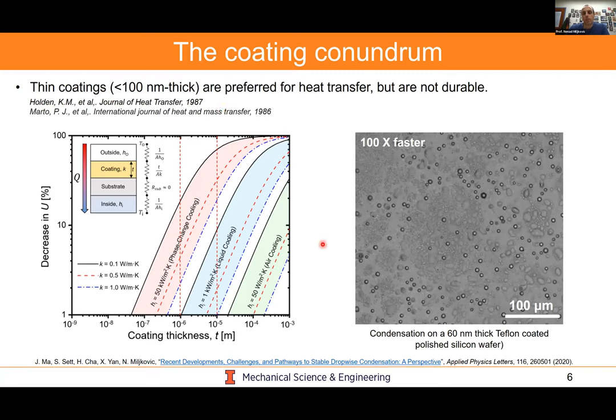they're not durable. And so what we could see here is if we were to actually look at what condensation, for example, of water looks like on one of these coatings, hopefully this video plays, maybe it's still loading. Essentially what you're going to see, and what you see here from the still image, is the formation of small water blisters. And what you're seeing here is small liquid droplets growing on the surface on the coating. And then these blisters form beneath the droplets, which actually delaminate the coating and remove it from the surface.